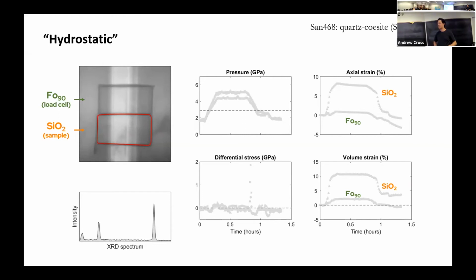But what you're going to see is we'll just sit in the alpha quartz stability field for some time. We'll get a pressure ramp up into the Coesite stability field. We'll hold there, and then we'll bring pressure back down. You'll see the live radiograph images flicking through. As a reference, I've drawn a red box around the starting dimensions of our quartz sample. And then we've also got our XRD spectrum. So you'll see this peak go away and be replaced by those two Coesite peaks that we were looking at before.